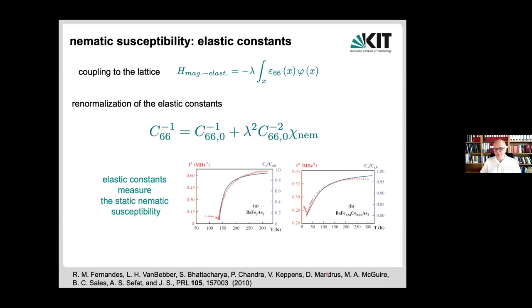The experimental work here was done by David Mandrus and Veronika Keppens at Oak Ridge at a time. So you see the softening of the elastic constant, essentially the divergence of the nematic susceptibility as you approach that transition. And you have an idea that there might be some underlying nematic degree of freedom being critical.